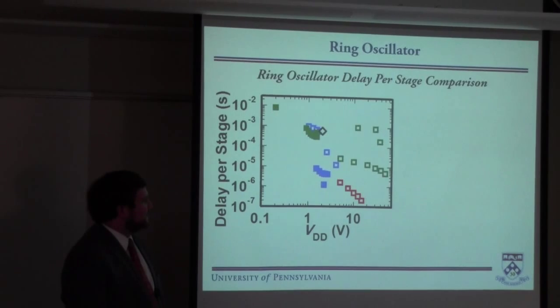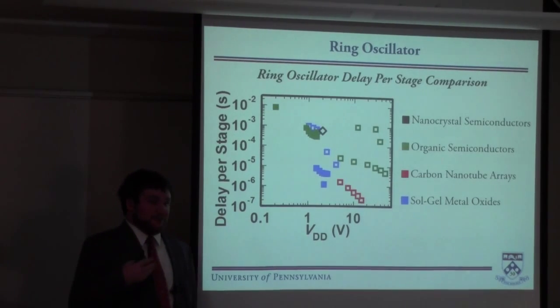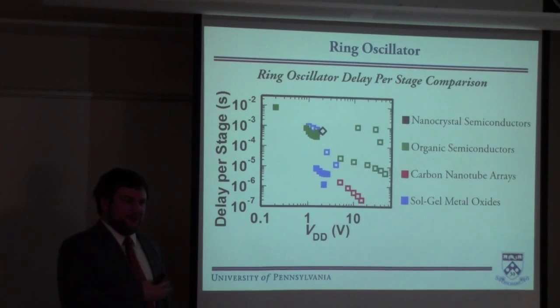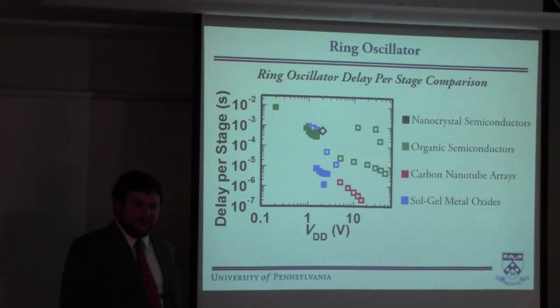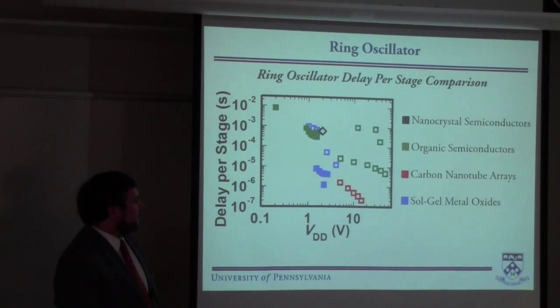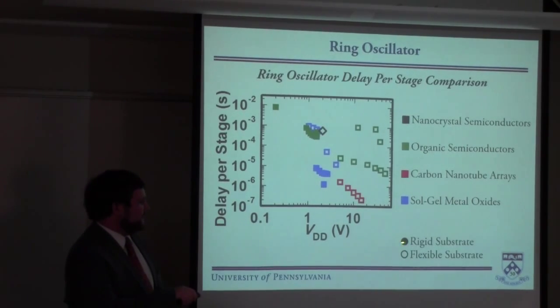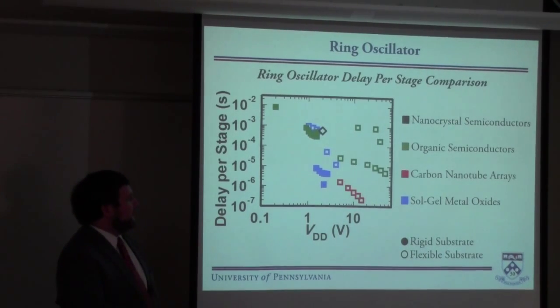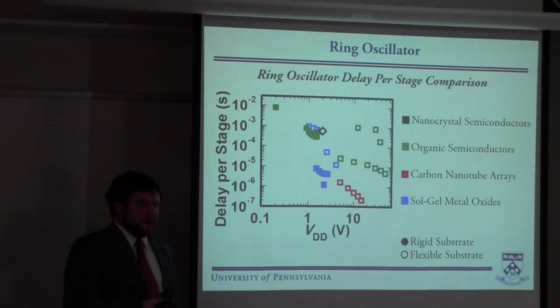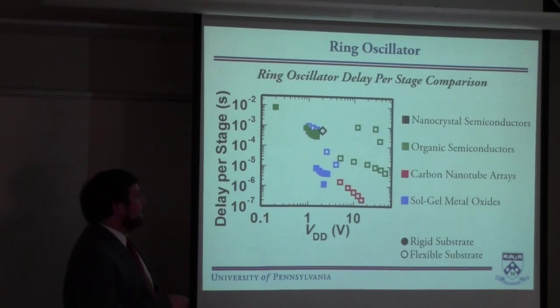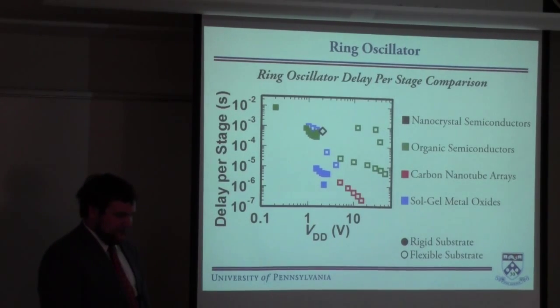And that brings up, what is a comparison with other technologies? So this is focusing on solution processable materials only, because that's the area where we really want this technology to become viable. The filled symbols are rigid substrates, and the open symbols are flexible substrates. So this includes carbon nanotubes, organics. This nanocrystal spot was the previous work that I mentioned earlier with the shadow masks. Again, very, very slow, because you want to push down into this corner as much as you can, basically the goal on this plot.